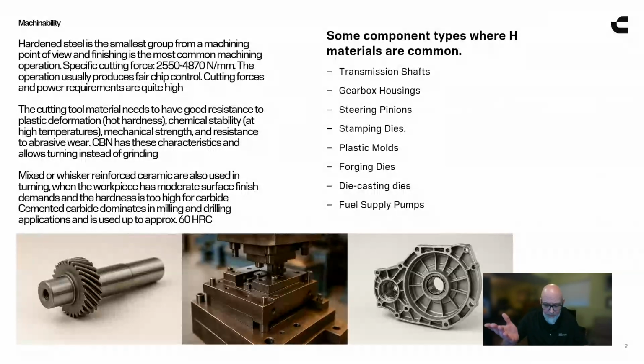There is something of an offset there, right? The higher tungsten carbide you have, the less cobalt you have, you lose toughness. So if there are any interrupted cuts or any instabilities in the process, with a high hardness insert, you really risk chipping it out, breaking it, fracturing it, because they're just so much more brittle. That moves us into the next segment: what makes heat-treated machining successful? What I can tell you is to mitigate those shocks, we like to run them high speed, light cutting parameters, so light and fast.